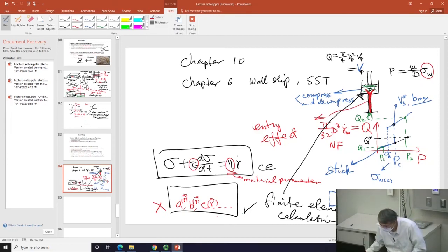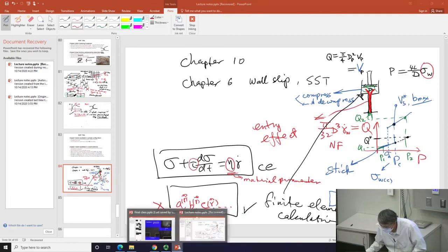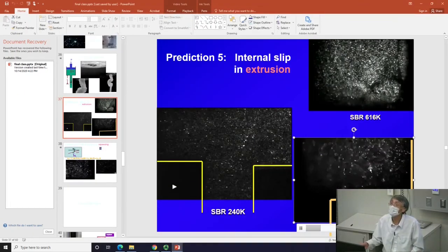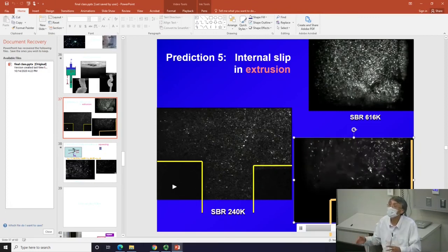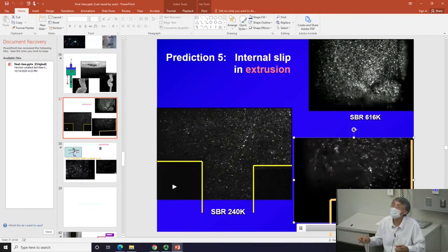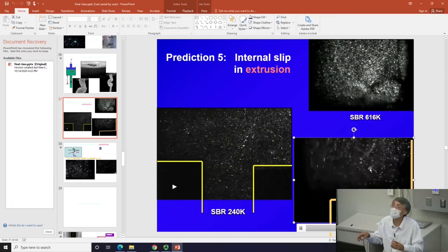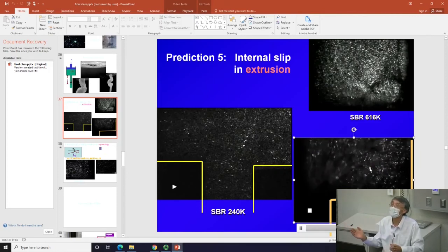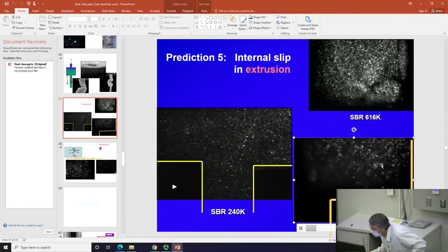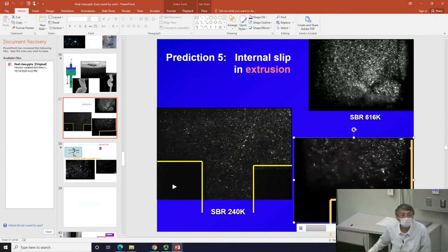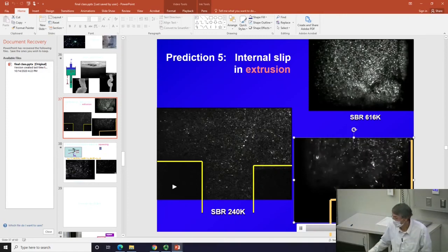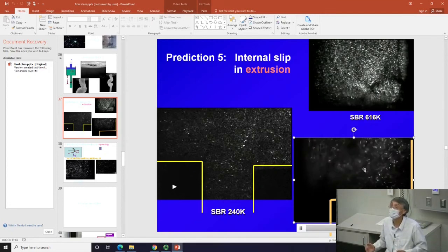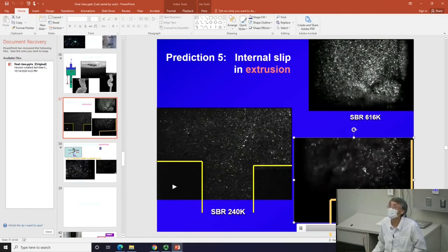I'm claiming, folks, that what we observe here is equivalent to saying that you need a constitutive equation where the A and B and C are spatially dependent. Why do I say that? Because here, the ABCs involve an entangled state. And here, at the boundary, the ABCs involve a disentangled state. Of course, they are different parameters.